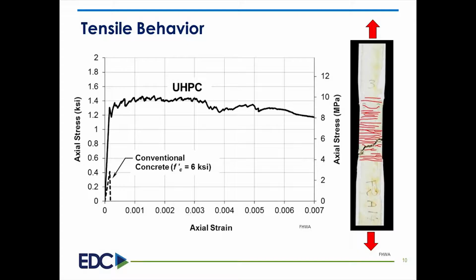But more importantly, the behavior is fundamentally different. With the conventional concrete, after the first crack, the concrete loses all its tensile strength. With the ultra-high performance concrete, after the first crack forms here, the tensile strength drops slightly, but then it goes up again as the fibers extend across that crack. And then the next crack forms, and the strength goes up again. And we get this sawtooth behavior as the tensile stresses are transferred from the concrete to the steel fibers.